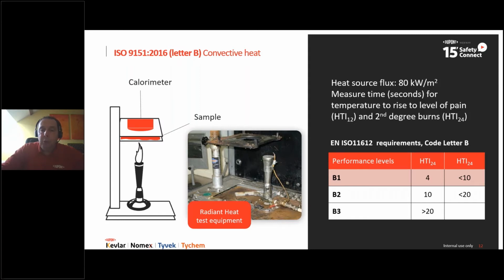And then you get the performance level between B1, the lowest, and B3, the highest. Now, if it takes more than 4 seconds, but less than 10 seconds to achieve this point of burn, then you have a B1 level of performance. If it takes between 10 and less than 20 seconds, you have a B2 performance. If it takes longer than 20 seconds to achieve the level of pain, you have a B3 performance in the convective heat test.